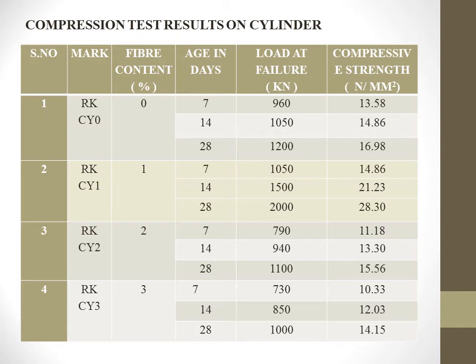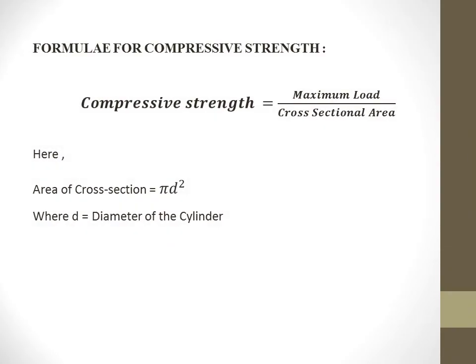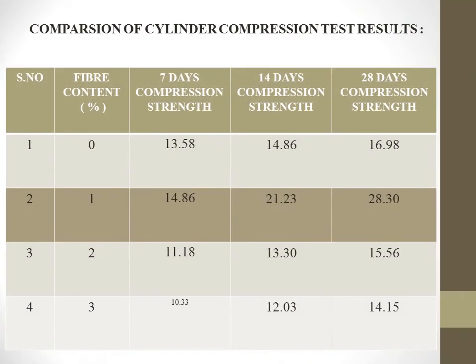With 2% addition, the compressive strength was found to be 15.56 after 28 days of curing, and with 3% addition of bamboo fiber, the compression strength had decreased to 14.15 Newton per mm square. This is the formula which we had used for finding out the compressive strength, and this is the comparison of cylinder compression strength test results.